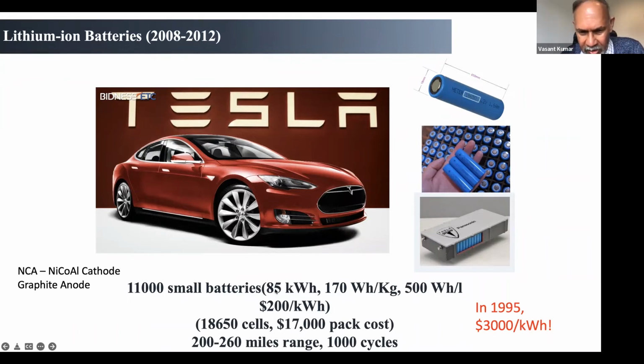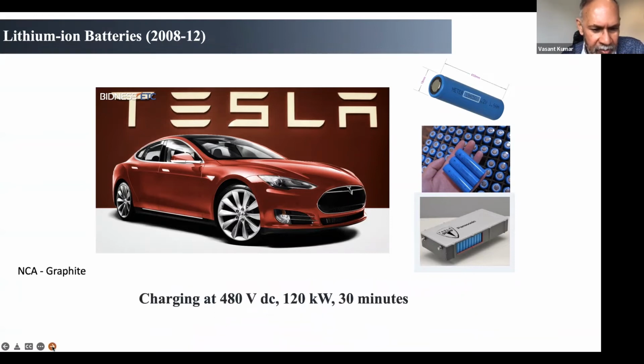And the metrics that the Tesla car used are shown here. The pack cost was estimated to be about $17,000. Most of the cost of the battery is actually the materials in it, especially because it uses cobalt. It's quite expensive. And the initial range was around 200 miles and 1,000 cycles. It really changed the game quite rapidly after that. And the charging time was about 30 minutes.